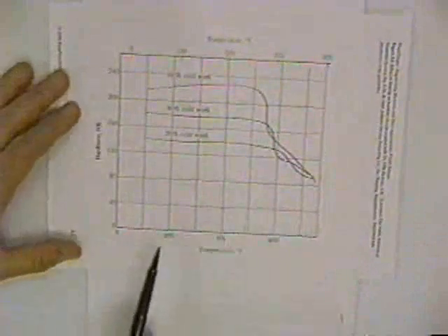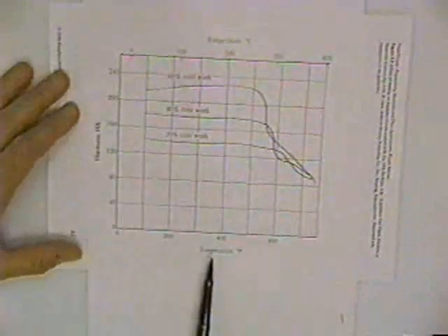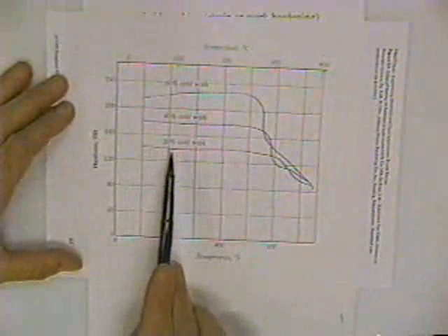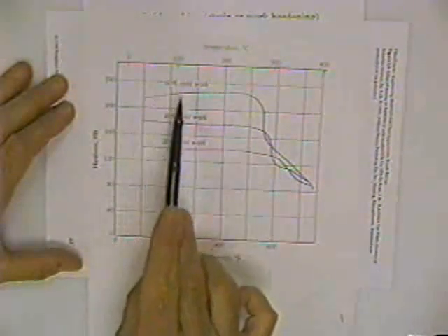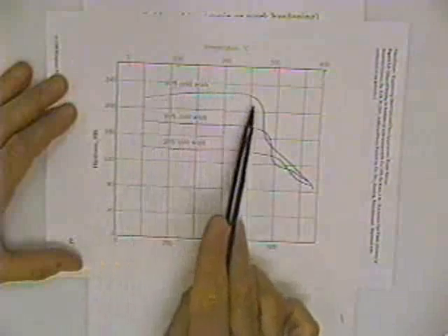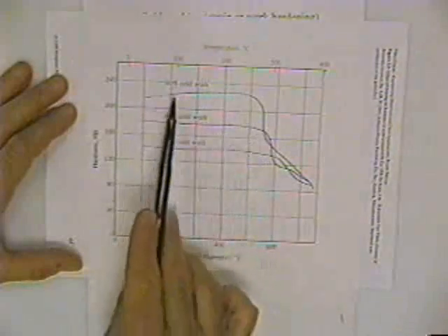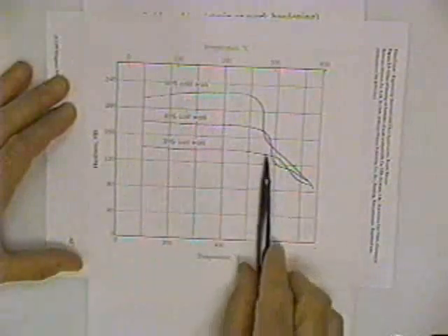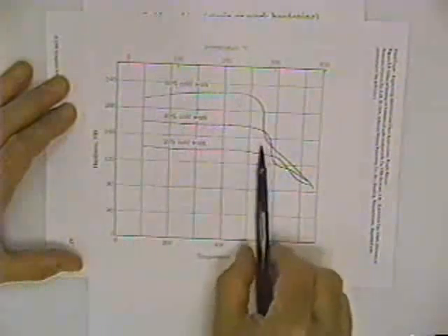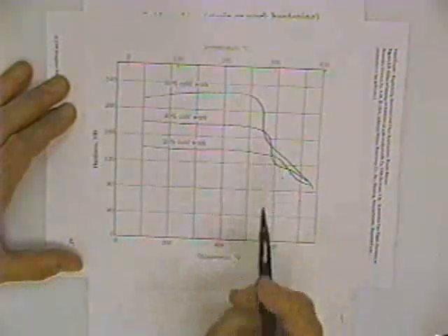The recovery process or recrystallization process is shown on the figure on page 25, and for the brass system, you can see that this is the recrystallization temperature and the amount of cold work, 20, 40, and 60, so this would be stronger, have less ductility, and you see the recovery process occurs a little earlier as the cold work increases. Provides more energy, it's a little easier for the process to get started. And so this would be the recovery, this would be the recrystallization.